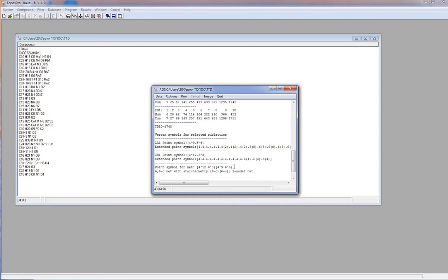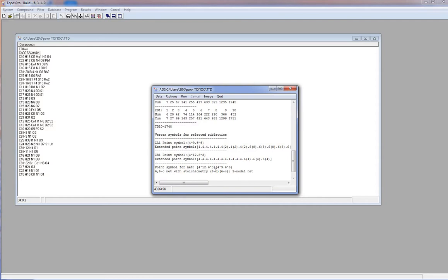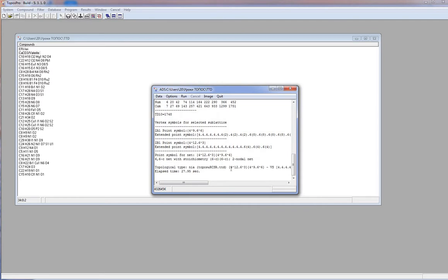This is point symbol for the net. It summarizes all point symbols for the non-equivalent nodes with their stoichiometric coefficients. This point symbol summarizes point symbols for two non-equivalent nodes contained in the net at equal ratio. This means that net is 6-coordinated. That is, all vertices are of degree of 6. This means that the net contains two topologically inequivalent nodes with different topological indexes. We determine topological type of the net with the point symbol and coordination sequence parameters. It has the nra topology.